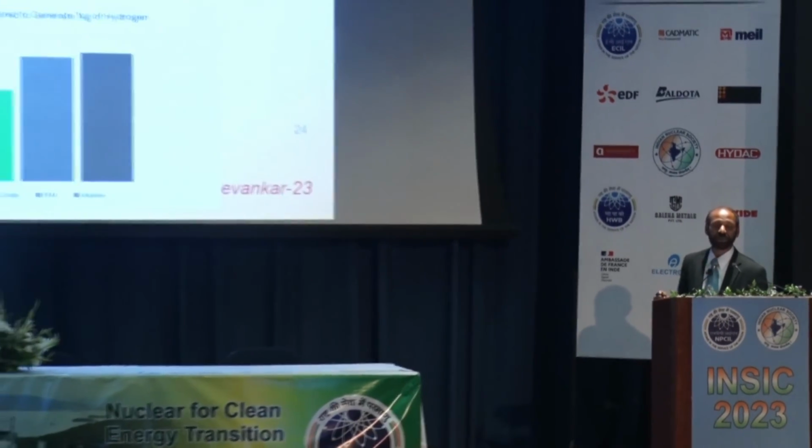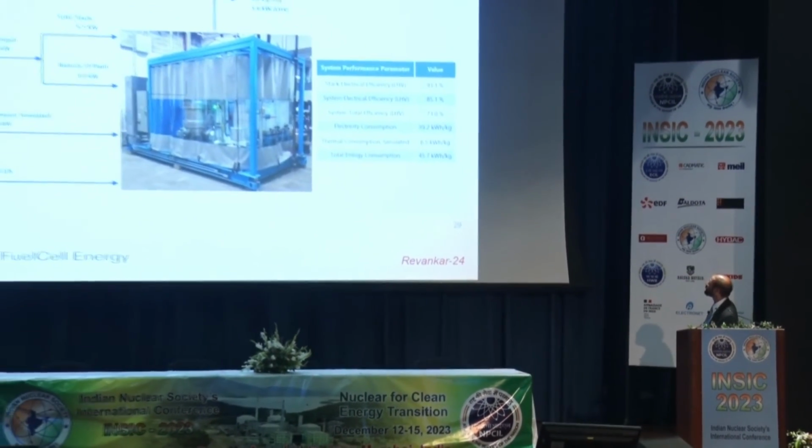This is a 1.1 megawatt SOEC product, and it shows a lot of its characteristics. And here is just the overall efficiency, as you can see, coming from the high temperature versus the low temperature electrolysis. Again, you are going to save quite a lot of energy. This is basically indicating that compared to the PEM or alkaline electrolyzers, the solid oxide energy requirements are substantially lower. It's almost at the minimum energy required, which is around 37 kilowatt-hours per kg, versus 50 and more for the other electrolyzers.